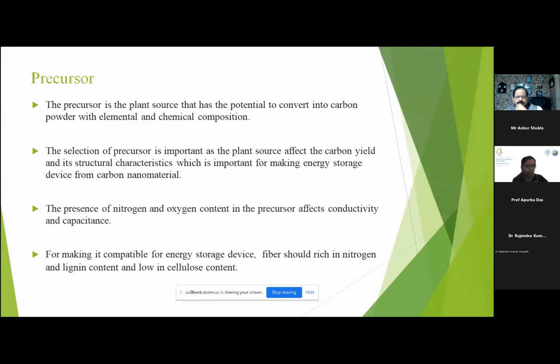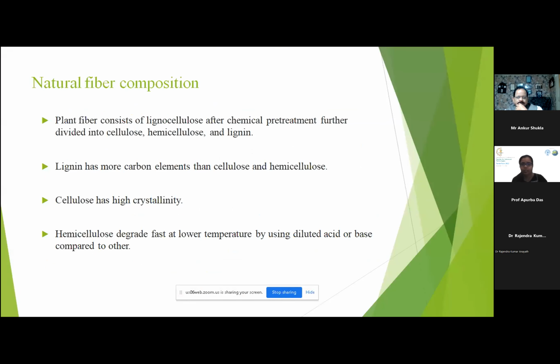After knowing the composition, here, lignin has more carbon element than cellulose and hemicellulose. Cellulose has high crystallinity, and hemicellulose degrades fast at low temperature using diluted acid or base compared to the others.